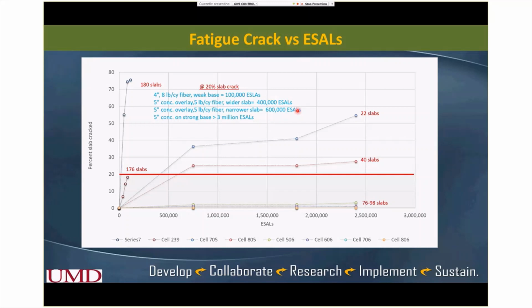So probably this particular research did not clearly show that we can increase the slab size. The slab size variation was 7 feet versus 12 to 13 feet in width. So this research says that maybe we cannot double the width of the slabs if we use fibers. Maybe by 1 foot, 2 feet, or 3 feet, which may not be a big deal, or may not be possible in construction. So we probably cannot double the size of the slab using fiber. That is probably what we are seeing from the results of the 2 thin unbonded concrete overlays.